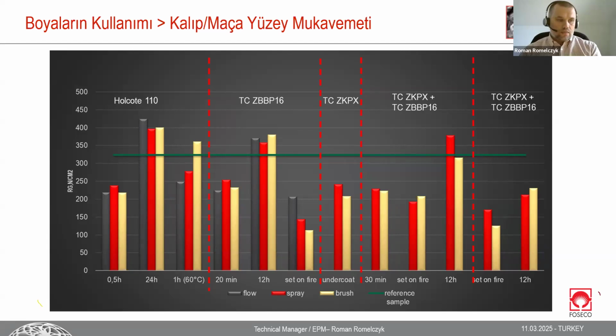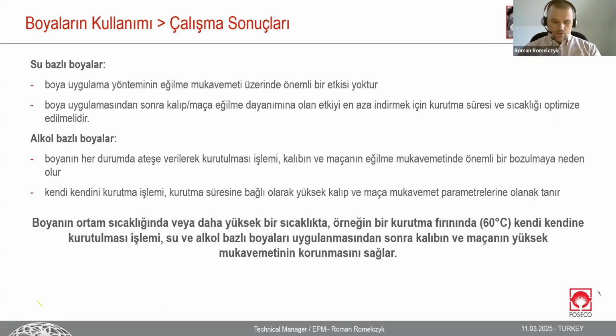So this is how sensitive the drying process of alcohol-based coatings is, and it's very important to understand that time is very important here. The more time between application and putting on fire, the better for the core, mold, and finally for casting quality. So the conclusions from this research were already presented to you: do not set on fire immediately. The best solution we can say is self-drying, or use an oven for drying. If not, leave the core or mold as long as possible to self-dry.